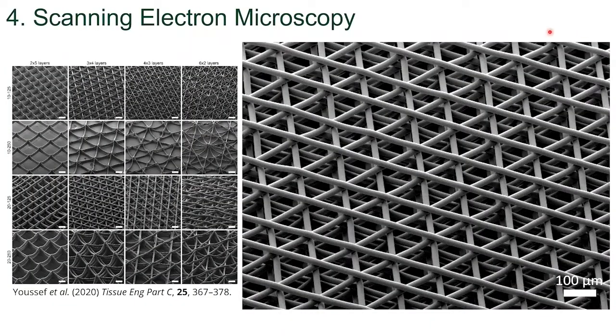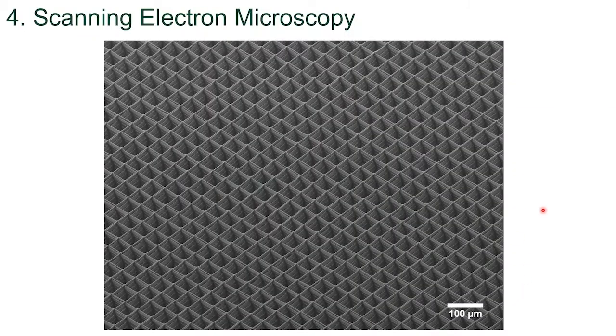These scaffolds can be written for a whole range of different patterns and structures for tissue engineering. A lot of work has been performed that shows the porosity is around about 80 to 90% and above. If we have a look at an example of a scaffold where the fibers are 2.5 microns in size and spaced 50 microns apart — this is probably the highest current resolution limit of the technology when making things as perfect in structure as possible — that's because there's some electrostatic attraction of fibers to the highest fibers already deposited, particularly when the spacing between them gets small.